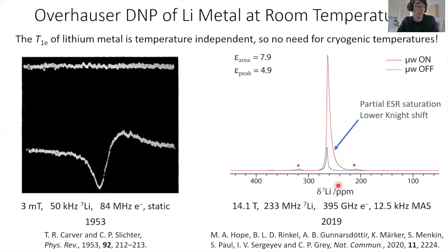And really, this shows us that we don't have very good saturation at all. If this was perfectly saturated, it'd be down at 0 ppm. And so we're actually only getting very small saturation. And that's because we don't have a large enough B1 field of our microwaves at this high frequency. And that's probably the main reason why we don't have higher enhancements. We just need more power.